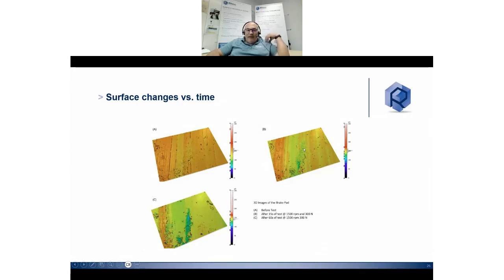And you see here, at the beginning, we don't have so many defects, and they increase during the test. We are removing some material and we are changing the topography of the sample. And we can do that because we have the upper rotary drive linked with a 3D microscope.